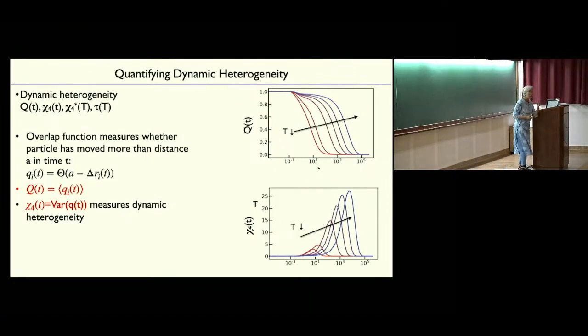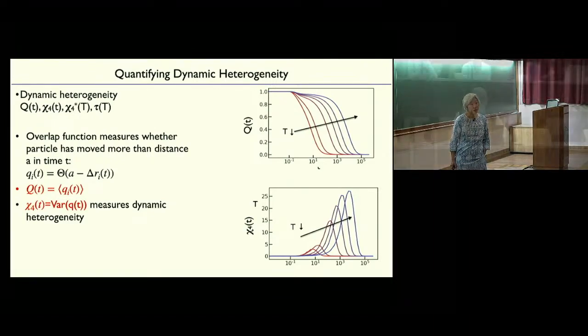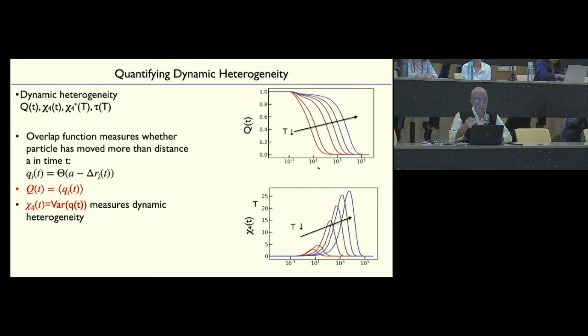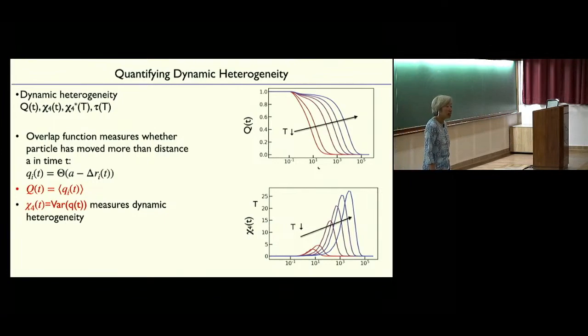And you see the same sort of behaviors. Actually, more precisely, the point is if you went in and made a sensitive measure of thermalness or non-thermalness, for example, the Harada-Sasa correlation-response difference, then depending on how you filtered it in time, you might or might not see that it's not thermal. If you blink too often, then you'll miss the non-thermalness. So even when you say it is thermal, at short enough time scales, you'll be able to see it. It's thermal on long time scales. That's absolutely right. In a filtered sense, at a long time scale, it'll be thermal.